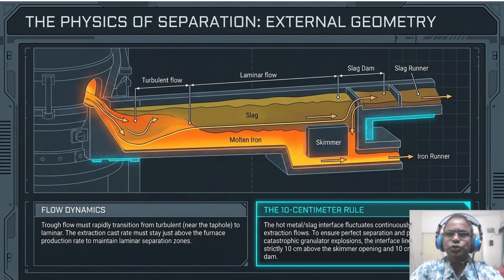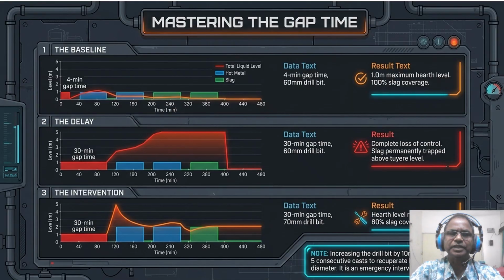So this chart shows three distinct scenarios for hearth management. Scenario one is our baseline, which is a 4-minute gap time and a 60 millimeter bit. This keeps the hearth level at a perfect 1 meter. As far as scenario 2 is concerned, here a 30-minute delay causes a complete loss of control. So slag is permanently trapped above the tuyere level.